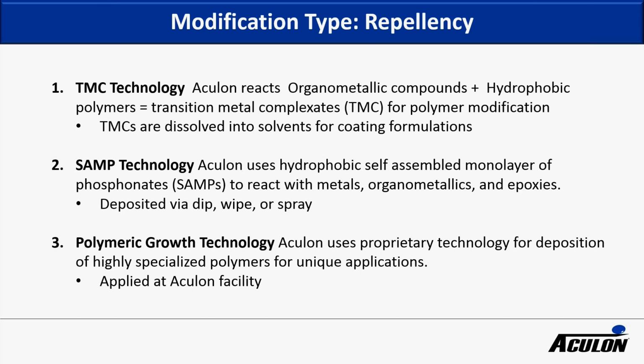So for repellency treatments, we have three technologies. The first one is based on what we call TMC chemistry. Here we're reacting organometallic compounds with hydrophobic polymers to form transition metal complexates, or TMCs. And these organometallics allow the polymer to bind to itself as well as the surface. The nice thing about this technology is it's widely applicable to a broad range of substrates. These materials are dissolved in solvents, and so they're in coating formulations that can be dipped, wiped, or sprayed on the surfaces.